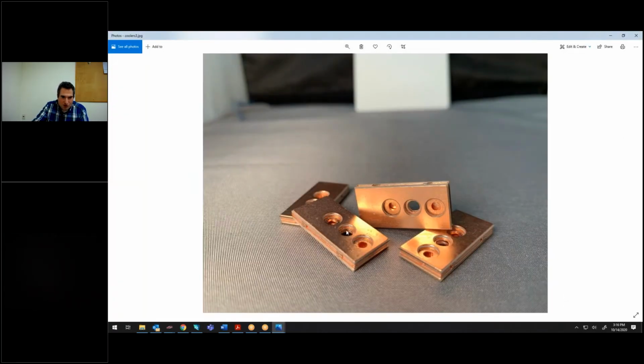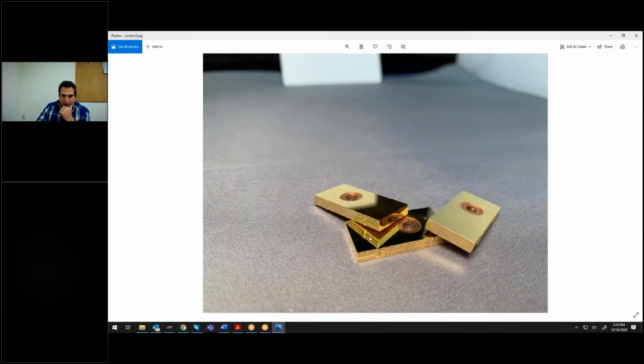And here is a version of a microchannel cooler, an isolated cooler, using direct bond copper structures as both the top and bottom. You can see here it's aluminum nitride on the top and aluminum nitride on the bottom. You can also see that AlN in there to create that same structure as you saw earlier, but just using direct bond copper instead of all copper.